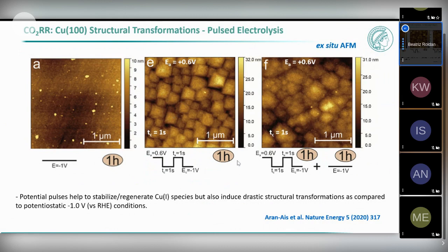If you run the reaction for 1 hour, applying the pulses, and then you just go to constant potential, the roughness somewhat remains, but here we don't have any copper plus left because we stay 1 hour again at this very negative potential. So this sample is going to have copper and copper plus roughness because the surface reconstructed, and this sample only has metallic copper and roughness.